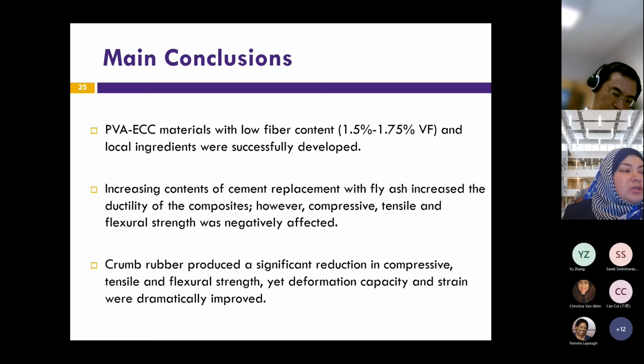So to conclude this part, the main finding that we found was that PVA ECC materials with low fiber content, 1.5% or 1.75%, and local ingredients is doable. We can produce ECC with these mixes. And increasing the content of cement replacement with fly ash increased the ductility of the composites, but it reduced the compressive, tensile, and flexural strength. Crumb rubber also had a significant reduction in compressive, tensile, and flexural strength, yet the deformation capacity and strain were drastically improved.